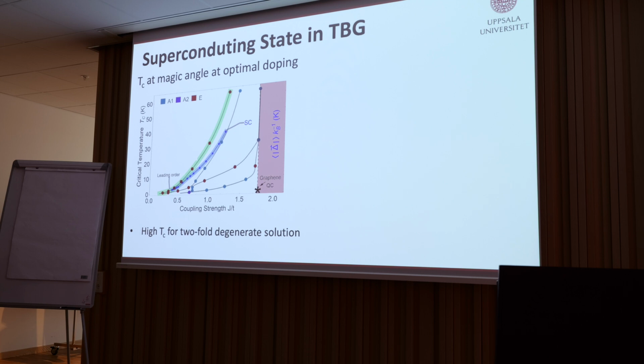And it turns out that the leading order belongs to the two-dimensional irreducible representation E, and it's this green state here. It goes down to quite a rather small coupling constant here, and you still get a substantial critical temperature. So you can get high Tc in this two-fold degenerate solution.